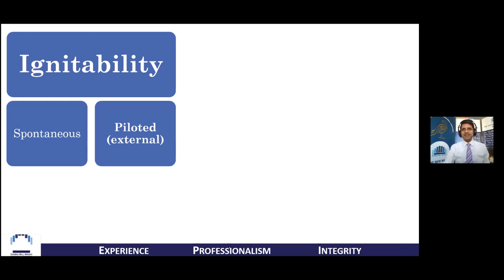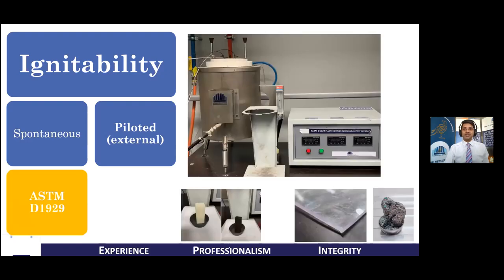So how do we quantify this for being able to be used in contracts, in technical regulations? And I start with one of the tests, which is typically used for plastics, which is the ASTM D1929. What the D1929 does is that it uses a hot air furnace and it tries to arrive at a specific quantified number saying at this temperature, the product or material that has been put to test will spontaneously ignite, which means ignite on its own, or will ignite with the help of an external flame or an ignition.